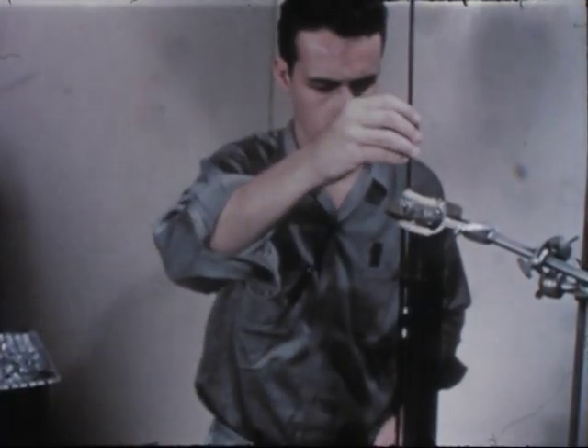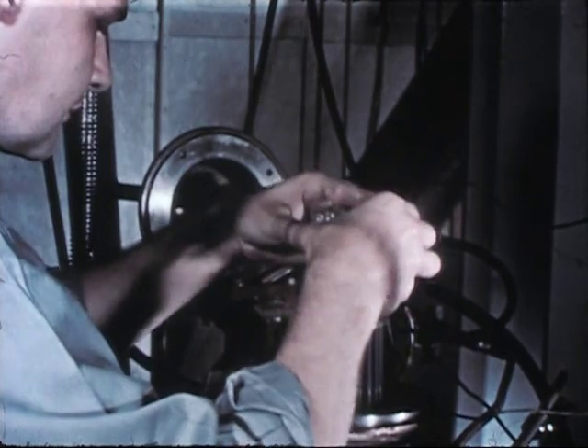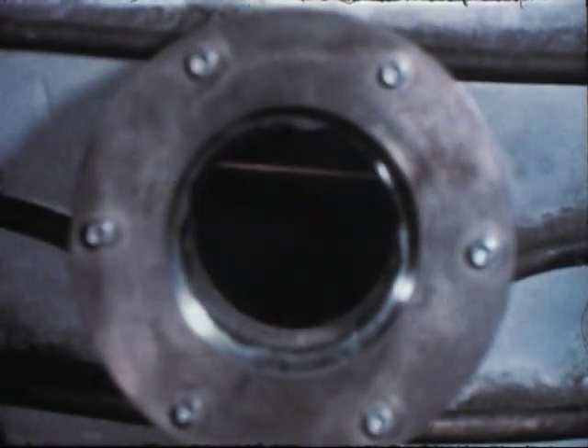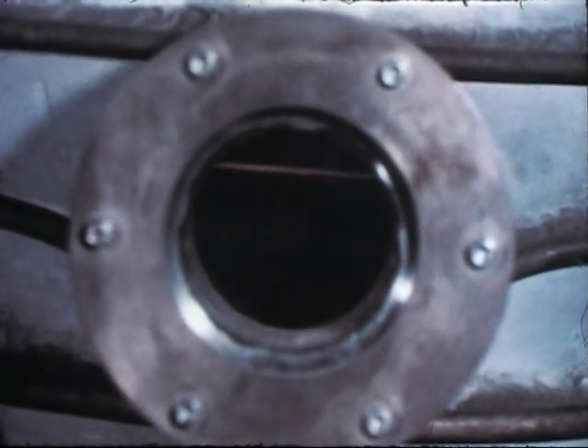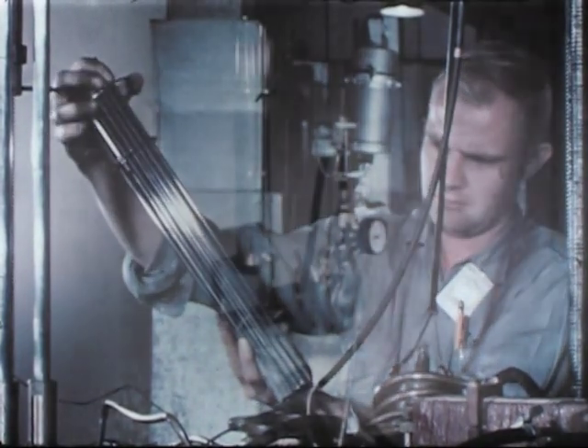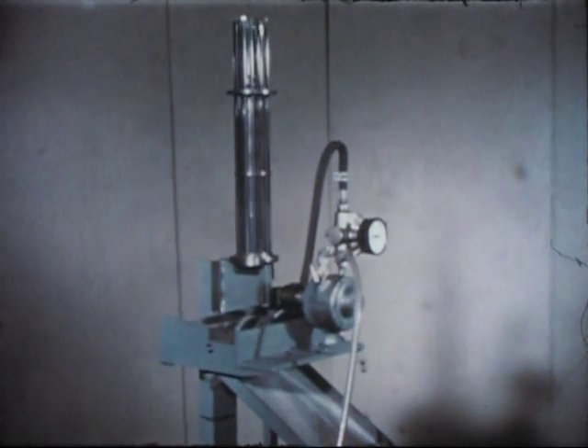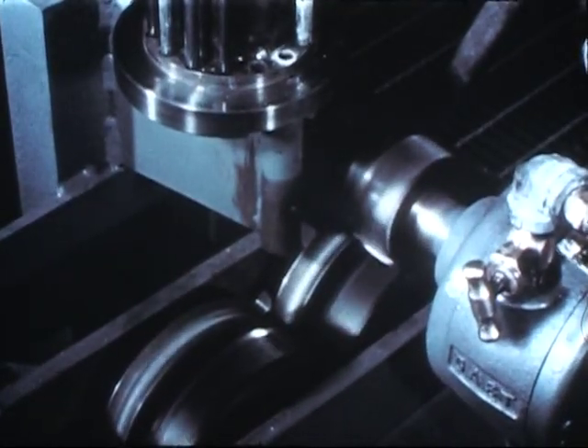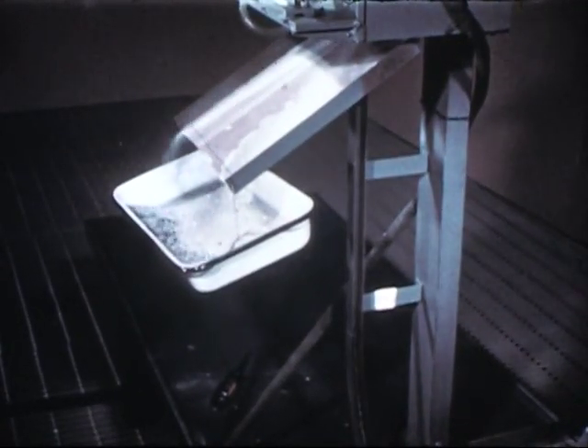A cluster of these tubes is suspended above the melting crucible. The ingot is vacuum melted and the tubes plunged into the molten alloy. At the same time, the furnace is pressurized and molten metal is forced up into the molds. Dimensional variations of the cast pins are essentially the same as those of the Vycor tubing. Removal of the precision-bore tubing is accomplished by crushing. The finished fuel pin is brushed to remove residual glass and requires no further machining.